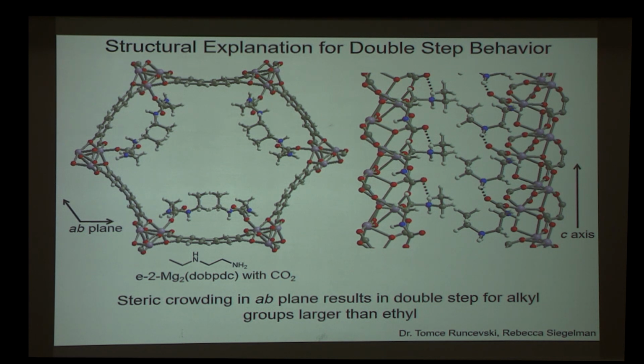And what you'll notice here is that this channel is not a perfect hexagon shape. The chains of ammonium carbamates tend to point towards each other in pairs. And you can see that the 2 ethyl groups from neighboring sites are very close to each other. This different perspective of the same crystal structure shows it even more clearly, where these ethyl groups are essentially making a van der Waals contact.